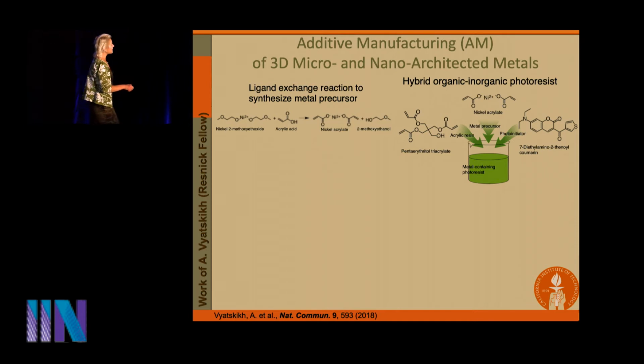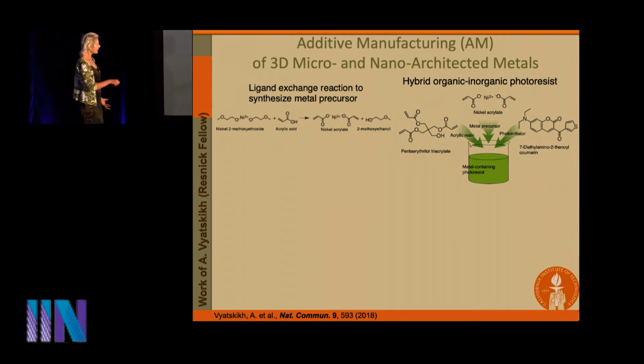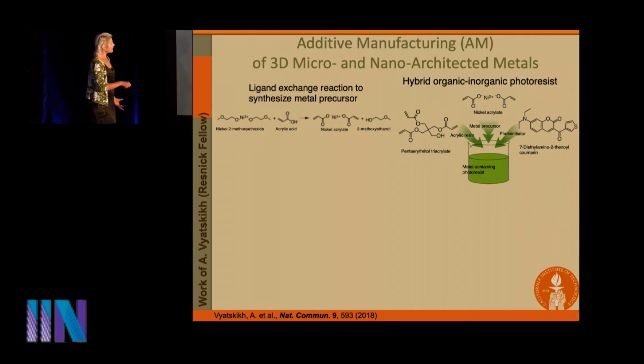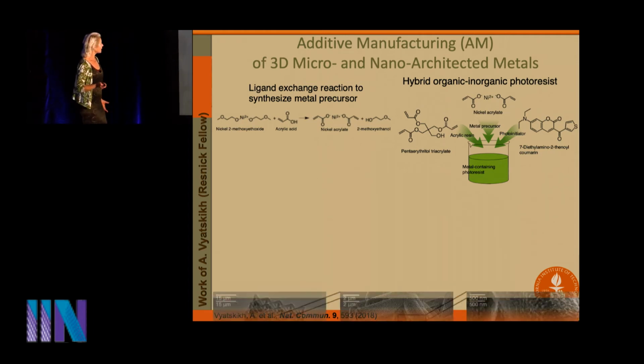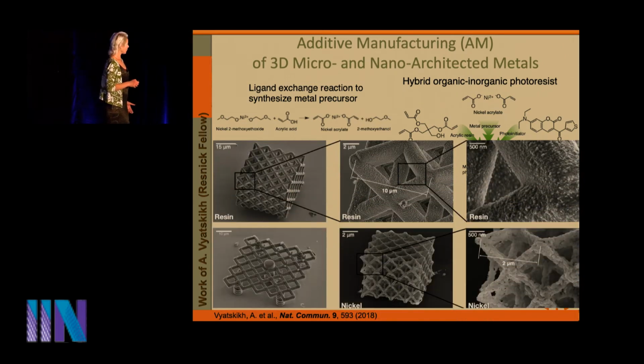So when we mix these organic and inorganic parts, so the acrylic resin for cross-linking, and then this nickel acrylate, as well as a photoinitiator, this creates a resin that could be amenable to light. And at the time, we didn't know if it was going to work, and we got extremely lucky because it did. So what you see is that this is the nickel-containing resin. Look at the unit cell size here. It's about 10 microns, and the beams here are roughly 2 microns or so. So this is an organic, metallo-organic compound.